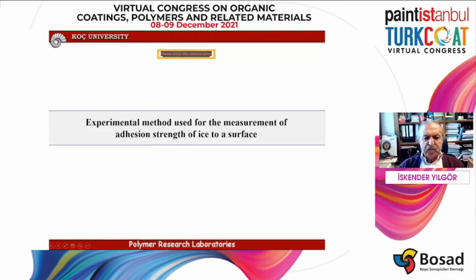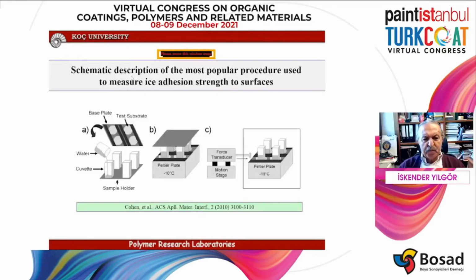Now, of course, we have to design experiments to measure the strength of ice, its adhesion strength to the surface. And here also, there are several different approaches. One that's very widely used is shown in the next slide. Here what you do, you have your samples on the test substrate. And then you have these cuvettes, usually polystyrene cuvettes. You fill them up with water to almost half, then put your sample holder on top of this and turn it around, and then freeze it at -10 degrees in this case.